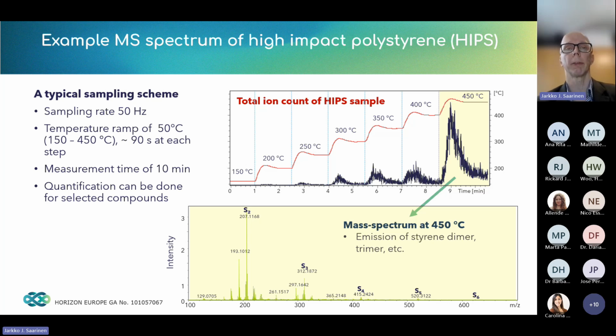So we start from 150 centigrades, and then we move on to 450 centigrades, as shown here on top at the total ion count of the high impact polystyrene sample. This is the total ion count spectrum on top, and then from each of the different segments, we can run the mass spectrum analytics. And for example, here, highlighted by the yellow background, the 450 centigrade emission, we do see